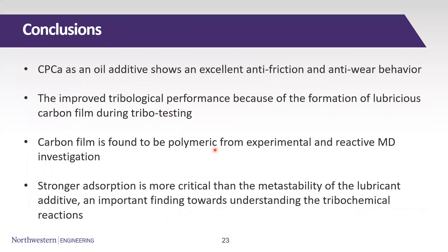In terms of conclusions: we showed that CPCA as an oil additive is able to show excellent anti-friction and anti-wear behavior, and this improved tribological performance is attributed to the formation of lubricious carbon tribofilm. Based on our investigation, this tribofilm is in fact polymeric, although it can show features such as D and G bands in the Raman signal at room temperature, which are sometimes misconstrued as a DLC film — so caution must be taken. Lastly, stronger adsorption is more critical than the metastability of the lubricant additive, representing an important finding toward understanding tribochemical reactions.